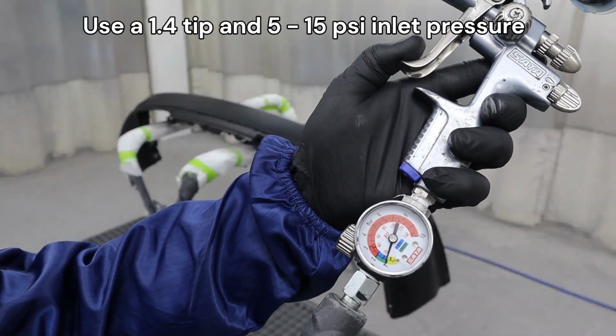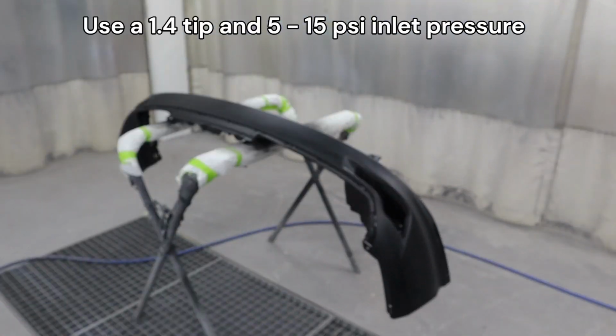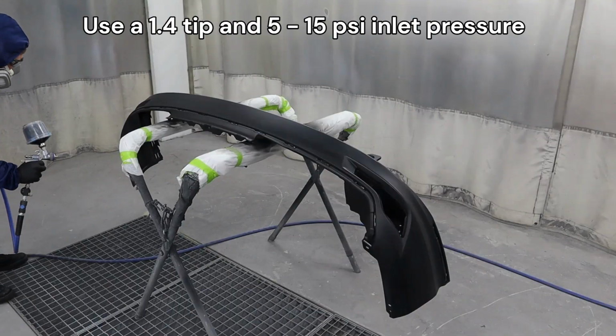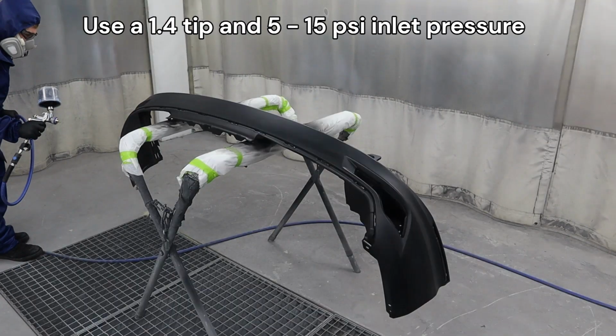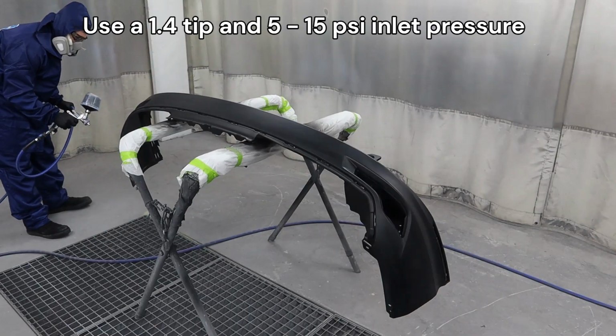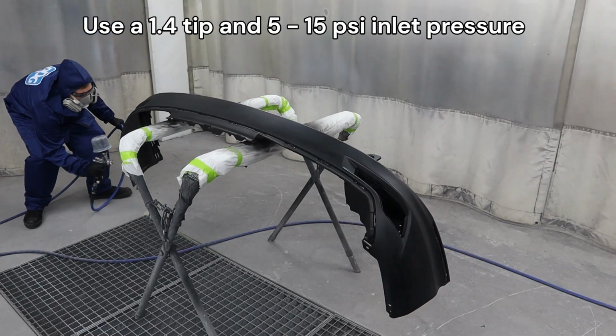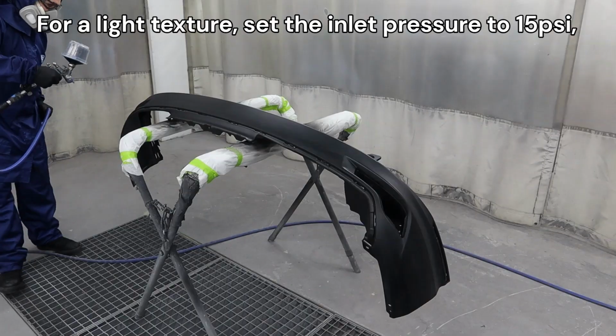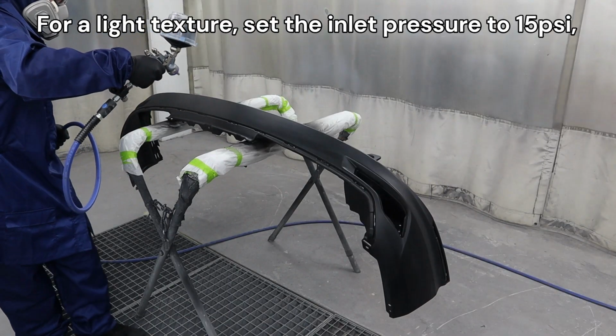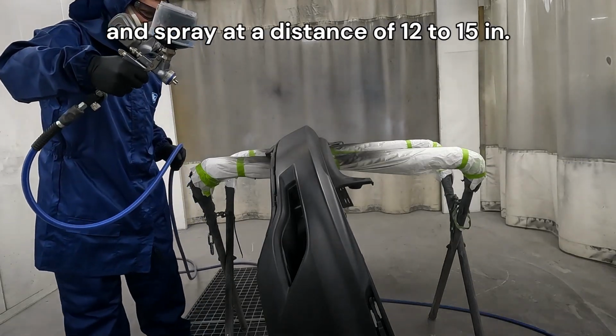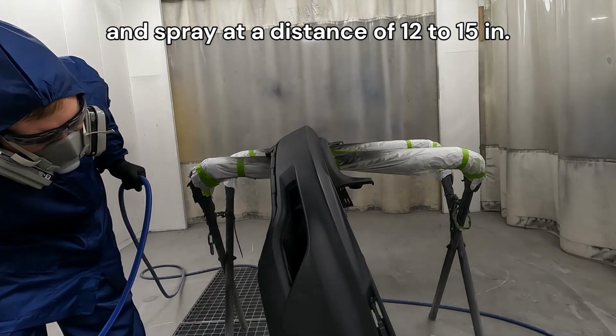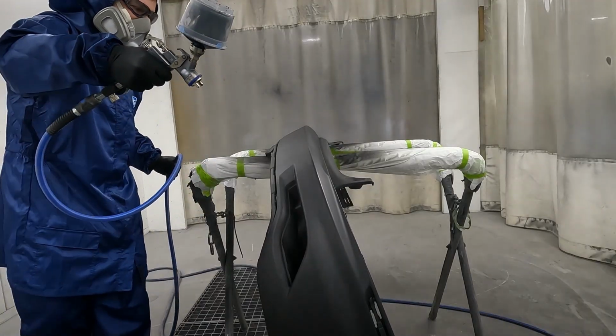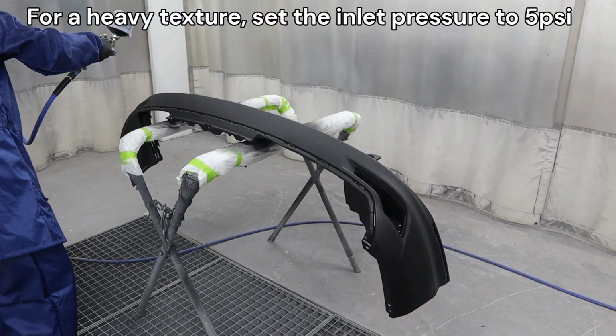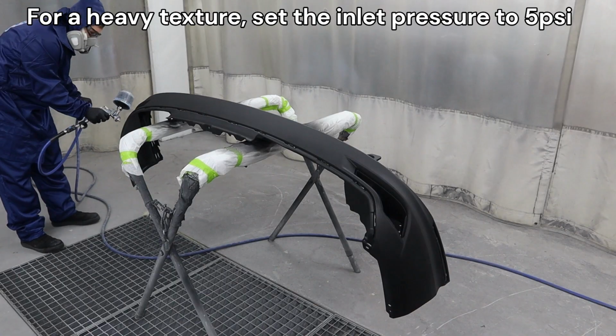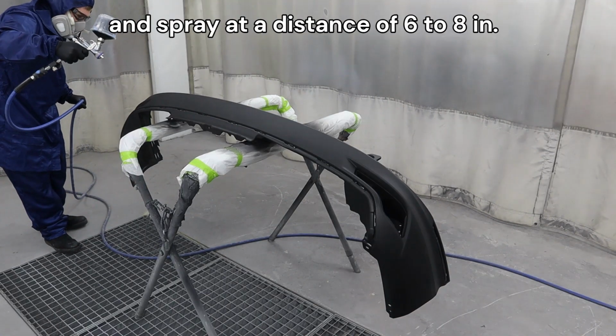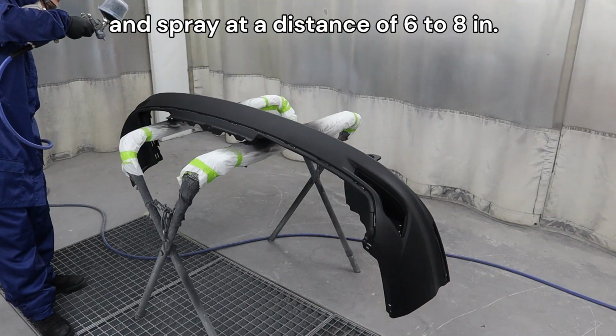Use a spray gun equipped with a 1.4 spray tip and an inlet pressure of 5 to 15 psi to apply the texture product. Pressure and distance from the part will directly affect the grain of the texture. For a light texture, set the inlet pressure to 15 psi and spray at a distance of 12 to 15 inches or 30 to 40 centimeters from a part. For a heavy texture, set the inlet pressure to 5 psi and spray at a distance of 6 to 8 inches or 15 to 20 centimeters from the part.